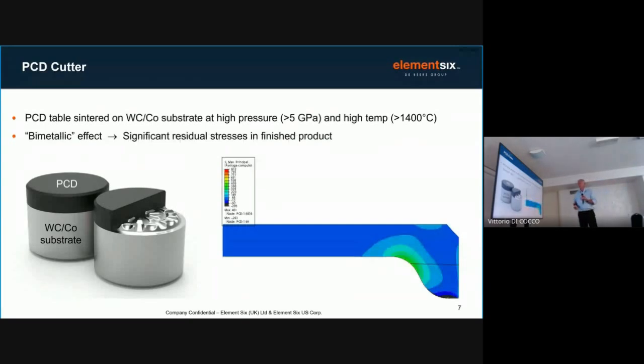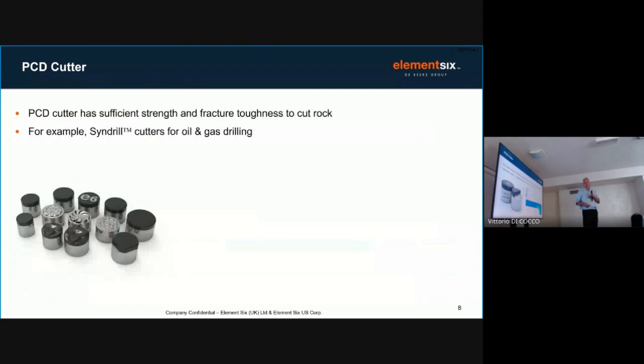Now, when you're sintering diamond, you have to use very high pressures and very high temperatures. So that means that when you bring the material down to room temperature and pressure, you generate significant residual stresses in the product. So we're dealing with big inbuilt residual stress there, up to a gigapascal. Sometimes enough to crack the material itself if we haven't got the sintering quite right. So anyway, the bottom line is that we have wonderful hardness and sufficient fracture toughness to go off and cut